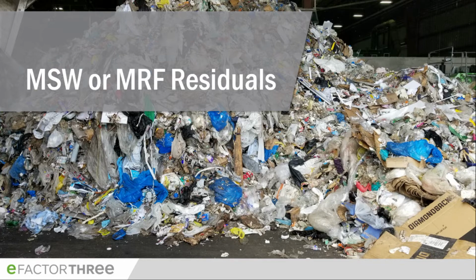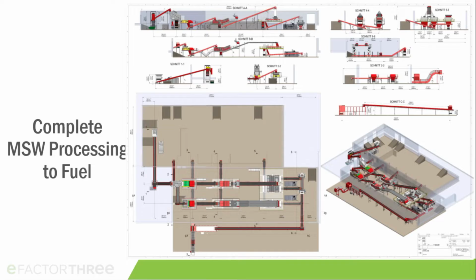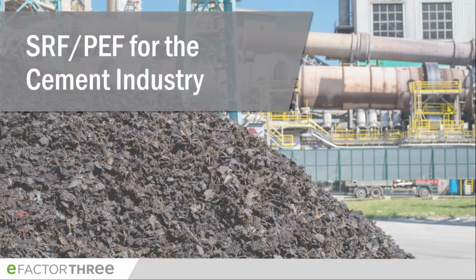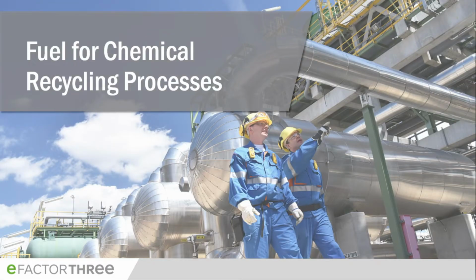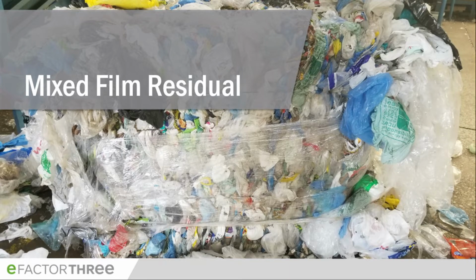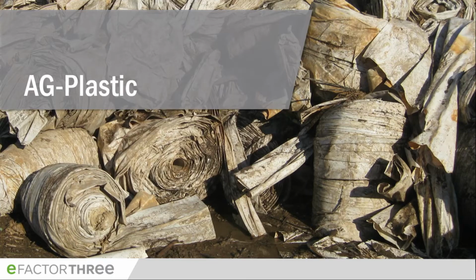When it comes to MSW or MRF residual, there's often the requirement to have a more complex system, including optical sortation and separation of organic fractions. With these technologies, we can create a fuel, and if it goes to the cement industry, it doesn't have to be cleaned much. But when we come into recycling, in the chemical process, there's a requirement to clean this material up. Mixed film residuals, mixed rigids, ag plastic. And ag plastic seems to be a very interesting commodity for pyrolysis because it's very hard to recycle material.